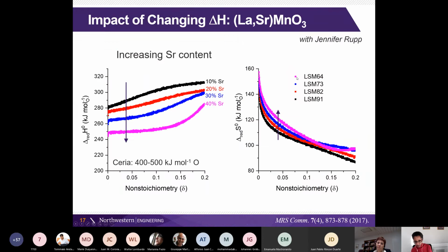So what does it mean in terms of changing the material? I told you that the hydrogen or the oxygen release is very difficult in ceria because its enthalpy of reduction is very large. So if we decrease that enthalpy of reduction, we'd expect a material to be easier to reduce. But you might think that it's also more difficult to oxidize. So we looked at lanthanum strontium manganese oxide, a material for which the enthalpy changes quite significantly with composition. Ceria was around 400 to 500 kilojoules per mole oxygen, and that's sort of the curved slope that I showed you. Here we're about half that, or a little over half that amount.